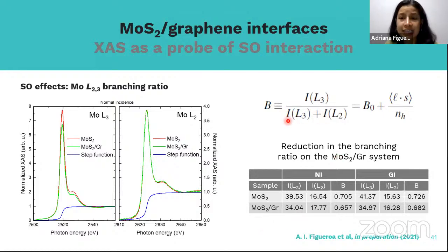And then we observed that indeed there is a reduction in the branching ratio on the stack of the MoS2 graphene. So it means that we have changes in the spin orbit interaction at the stack compared to without the graphene, which means that there is a probe of a spin orbit interaction, and at the interface of MoS2 and graphene, there are indeed some effects that are relevant or that are observed in this kind of systems of this stack.